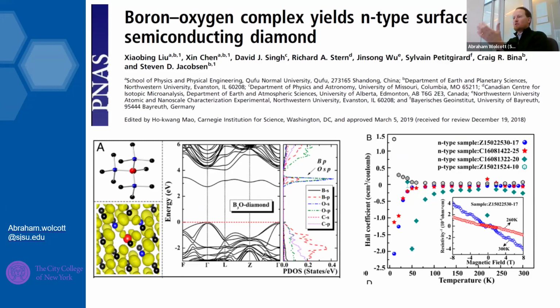So it has an N-type surface conducting layer, which we might be able to use with STM or to make devices that are N-type conducting. What's unique about this is that in this study, they used boron-doped diamond, which of course is a P-type dopant in diamond, commonly used for tribology and other electrochemistry applications, but they found that boron-oxygen mixed states allowed for conductivity to occur. So again, I would highlight this paper as a way to summarize the connection between bulk diamond crystallites and what we're seeing on the nanoscale as well.